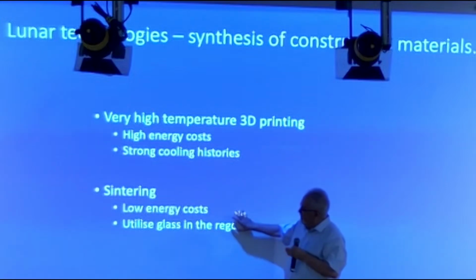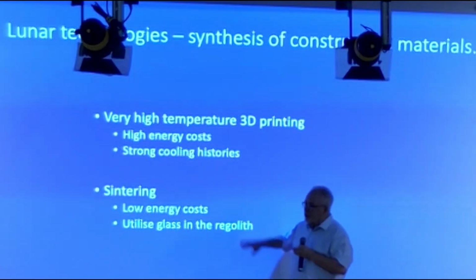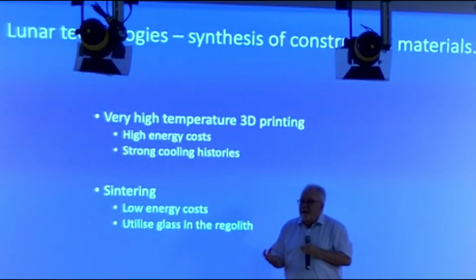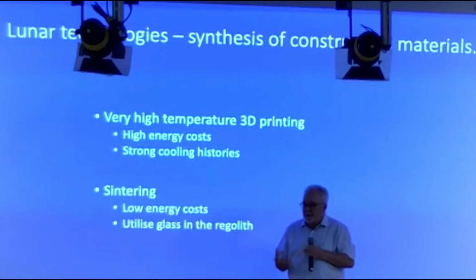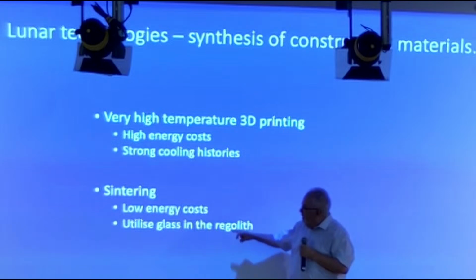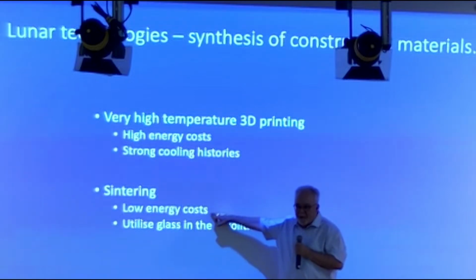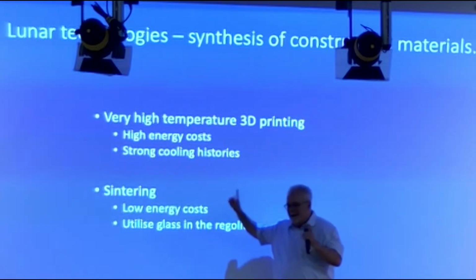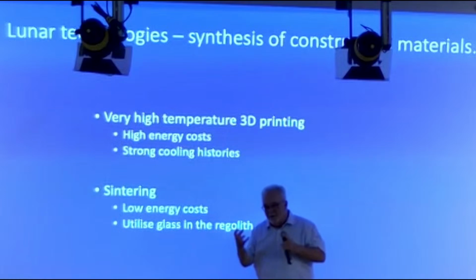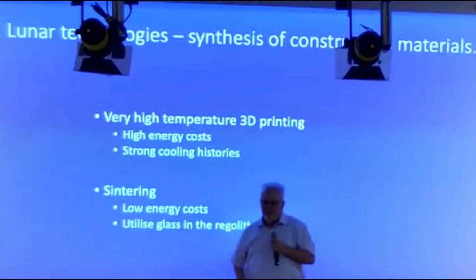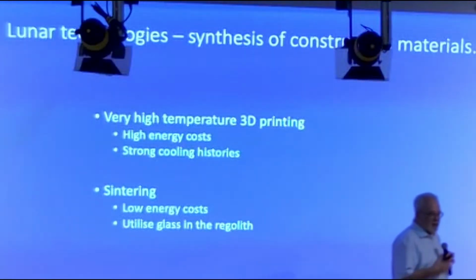The other way to do it is sintering, which means you just heat it up enough that it can slowly begin to stick together. That's Don Dingwell's version of sintering, okay? So from particulate material, you get solid material. This is how all ceramics are produced. You only have to go to half the temperature, maximum, maybe even less, so a lot less heat. And what is the best thing you can have if you want to reduce the temperature of sintering? Glass. And it's there. It's 10 to 25% of the rock already.